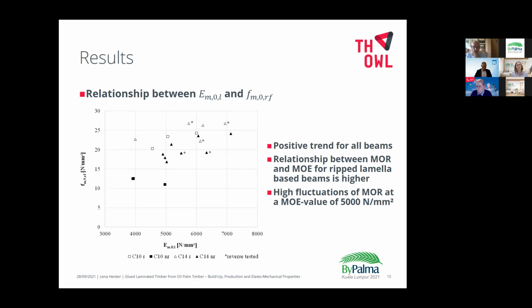This diagram shows a positive trend between bending strength and stiffness for all GLT beams. The correlation between strength and stiffness is higher for ripped lamella-based beams compared to the non-ripped lamella-based beams. There's a high range of strength values at an MOE of 5,000 newtons per square millimeter.